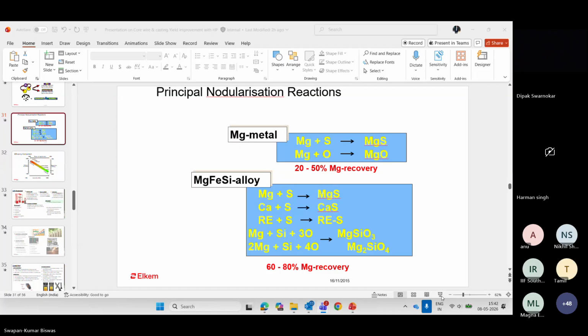Yes, yes, sir. So in pure magnesium treatment, that is magnesium metal, you are getting magnesium sulfide and oxide. There are other impurities or nucleation, but it is less. But in case of ferrosilicon magnesium treatment, below, you are getting all this ingredient: sulfide, oxide, MgSiO3. That is not obtained from this pure magnesium treatment.